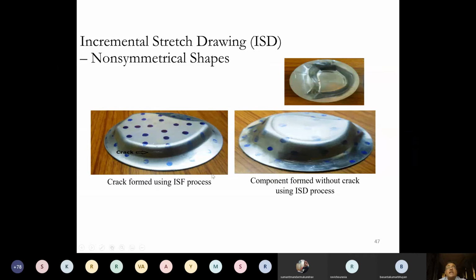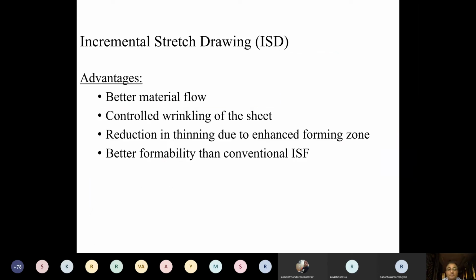The dots you can see are meant for the digital image correlation (DIC) technique. At the zones of stretching, you can see there was a circle before. After forming, the circles were converted into ellipses. So this helps us in finding out the major strain and the minor strain which has come into the component.